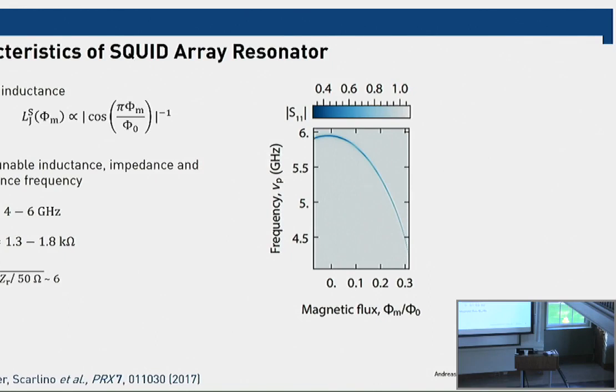And by analyzing this spectrum, you can extract the resonance frequency, and you can also learn about the impedance of this device. This particular device has an impedance of, say, up to 1.8 kilo ohms. And the ratio of this realized impedance to a typical 50 ohm impedance gives you the increase in coupling strength that you have realized. Because it's only the square root of that ratio, the coupling strength increases moderately.